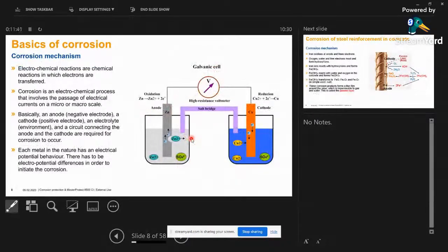Looking at the mechanism, we all know that corrosion is a purely electrochemical process. It needs to have an anode, it needs to have a cathode. We know that in case of concrete construction, the pH of the concrete is very high, 13, 14, and at that level of pH, it has a very strong passivation layer on the steel reinforcement, and therefore the steel embedded in the concrete is very well protected. So there is no formation of a galvanic cell. But what happens over a period of time, for various reasons? Let's say the quality of the concrete is not good, the structure is old, and there are fissures in the structure,